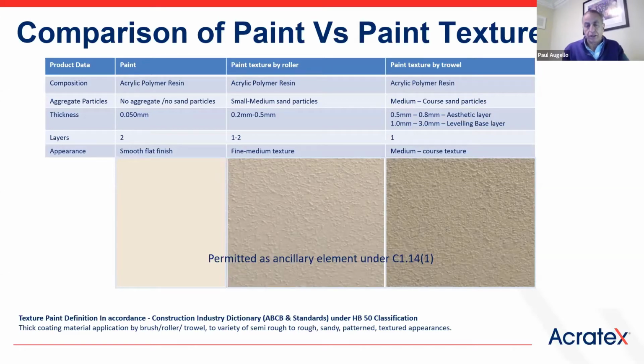These materials are generally applied at 0.5 to 0.8 of a millimetre, even over 1 millimetre. So we're talking all up around 1,000 microns in paint language, or under. But I suppose the underlying factor here is that all these sit on the same polymer resin, and we know that paint becomes exempt under the ancillary element under C1.14(1). In our interpretation, paint texture, whether it's roller applied or trowel applied, falls under the same definition through their composition.